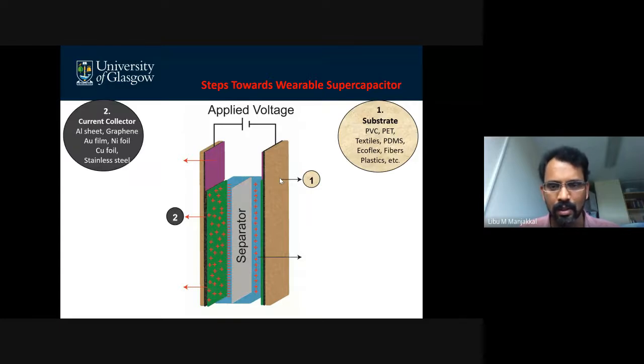Then on the top of the substrate, we need a highly conductive material. It's called a current collector. For a current collector, aluminum sheets are widely available now for packaging or many other applications. Or there are graphene film, or gold film, or copper sheet, copper foils, which we are using in our laboratory. So on the top of this textile, you can deposit your current collector in any method you can use, like a bonding method or screen printing or dip coating. You can convert your substrate to a conductive substrate, like on the top of that, you deposit your current collector.